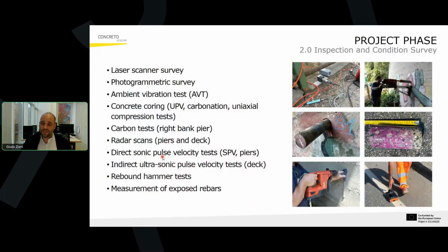In terms of the set of inspection activities that we carried out, at first a laser scanner survey, which was then followed by a photogrammetric survey, ambient vibration tests to assess the dynamic properties of the structure, followed by some concrete coring. Also in this case, the number was very limited, but we were able to carry out ultrasonic pulse velocity tests, carbonation tests, and uniaxial compression tests.